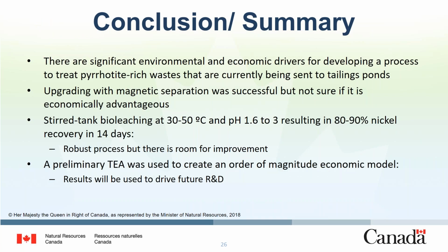So in conclusion from these experiments, there are significant environmental and economic drivers for developing a process to treat pyrrhotite-rich waste that are currently being sent to the tailings. Upgrading with magnetic separation was successful, but it's not clear if it's economically advantageous. The stirred tank experiments that we conducted demonstrated relatively good nickel recovery in the order of 80 to 90% nickel in 14 days, suggesting a robust process, but there is significant room for improvement. A preliminary TEA was used to create an order of magnitude economic model, and the results will be used to drive future R&D on this topic.